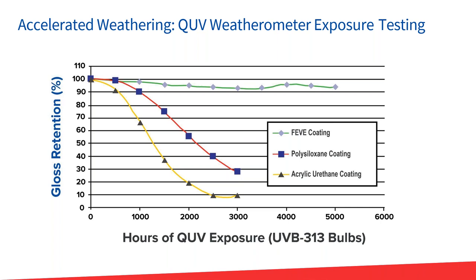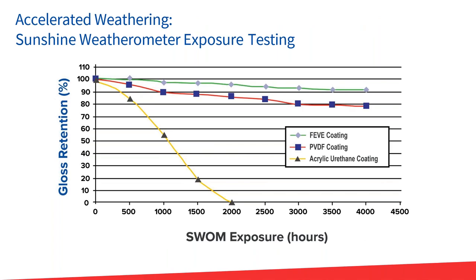So here you have a QUVB. That's a pretty high energy bulb. And so that really tears up more conventional systems. And that's where you see that gloss loss over hours of exposure versus an FEVE coating system. Here you have what we call a sunshine weatherometer. So it's basically another chamber where you have artificial bulbs that mimic UV light. This one is a little more representative of what sun exposure is.